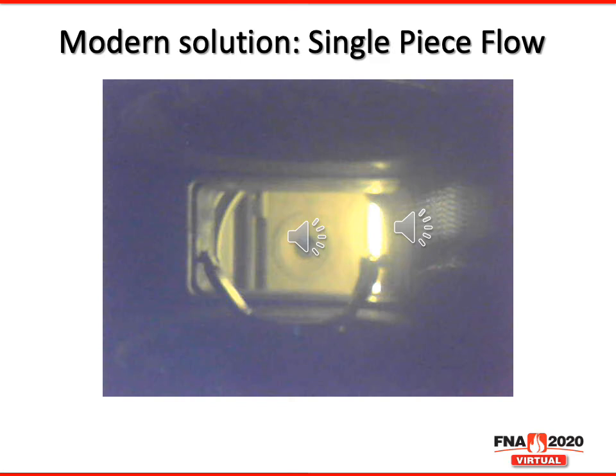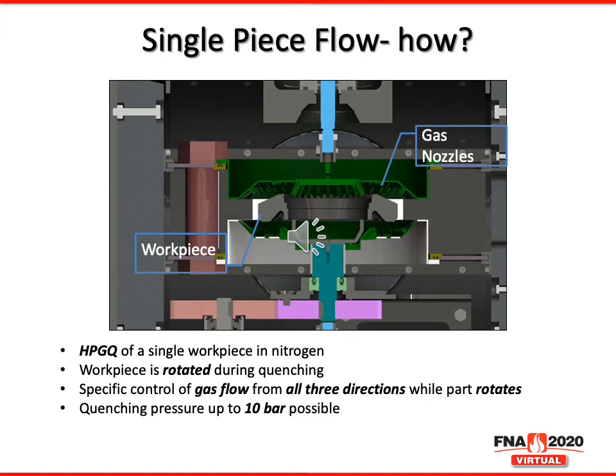As this video shows, this arrangement allows for rapid cooling in a very uniform manner. How? First, the part is inserted into the quenching chamber. It rests on a set of nozzles that then move to encapsulate it from both below and above. These nozzles are arranged in a pattern to allow for as much direct impingement on the workpiece as possible. Then, of course, like a normal single chamber vacuum furnace, this chamber is pressurized to up to 10 bar in nitrogen, and gas is then circulated through a heat exchanger and a fan through these nozzles around the part and back out.